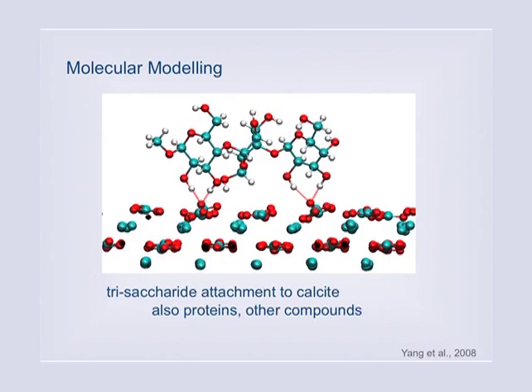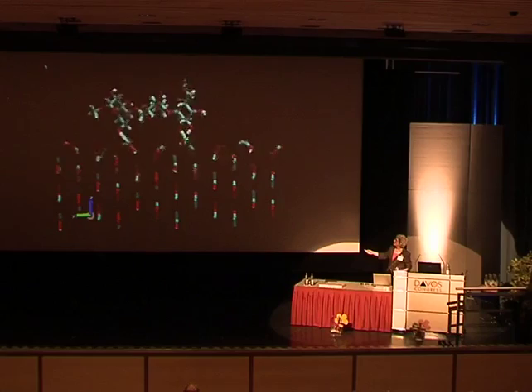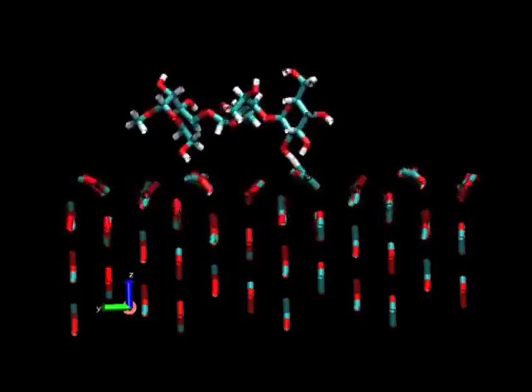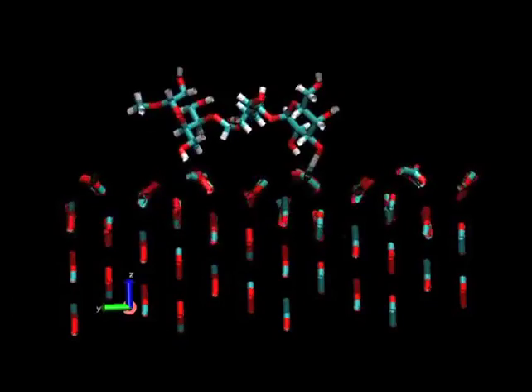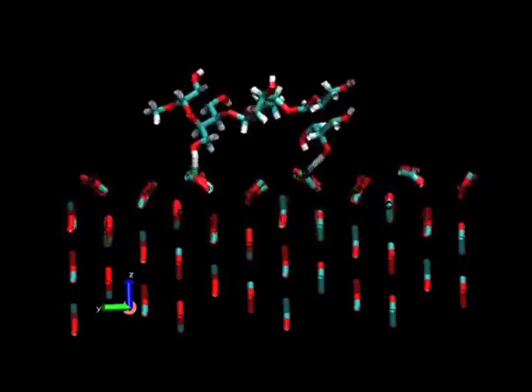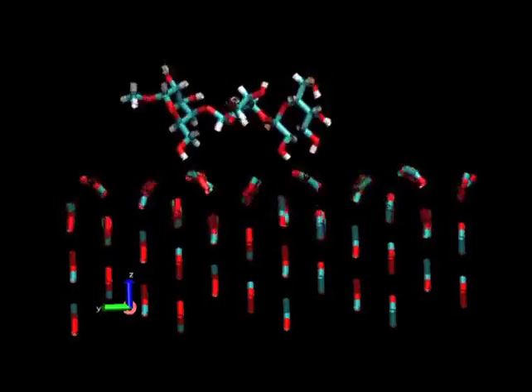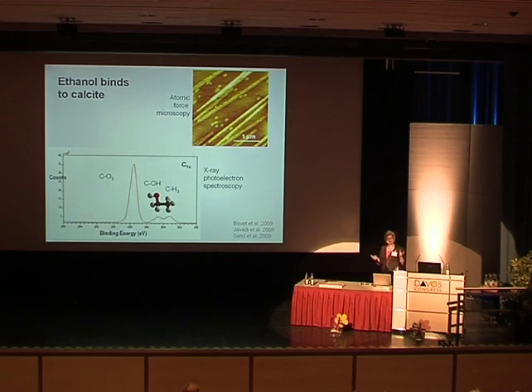And now I want you to watch the calcite underneath. This is the calcite, and there's the polysaccharide. Now watch the polysaccharide dancing on the surface of the calcite. And watch the calcite molecules, the calcite ions, moving. So you see now the polysaccharide is sticking, and it's got one foot down all the time. It's kind of like us dancing. We don't dance with both feet in the air all the time. If it danced with both feet in the air, it would float off in solution again. But it's got always a foot or two on the surface. And the foot is made of hydroxyl. So that got us interested. What is it about hydroxyl that makes it so sticky?